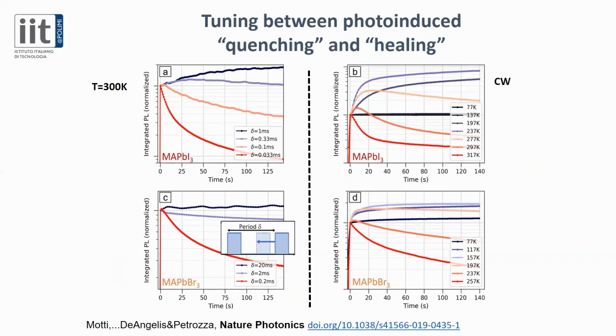So you can actually observe both quenching and healing of defects by changing the experimental conditions. On the left, for example, I'm showing the integration of photoluminescence over seconds when we change the time between illumination and dark for your sample, so the repetition rate of our laser in this case. And what you see is that closer to CW condition, you observe a quenching. When you reduce the illumination time, you start observing a healing phenomenon.